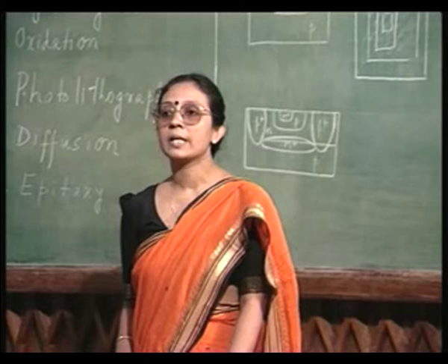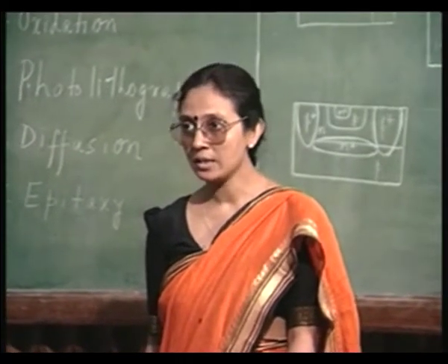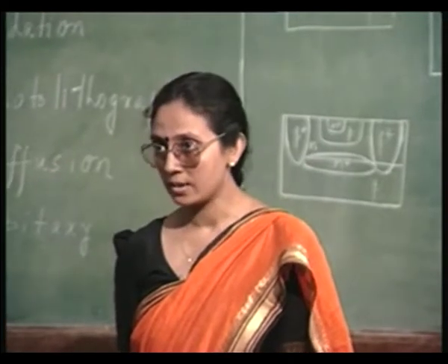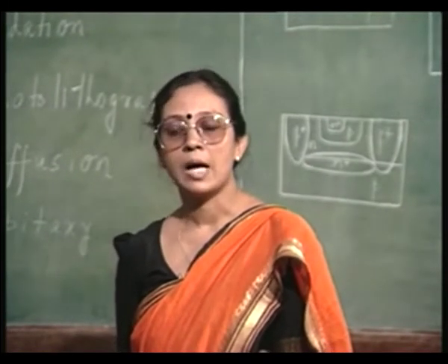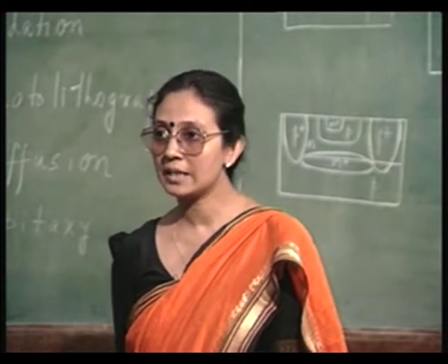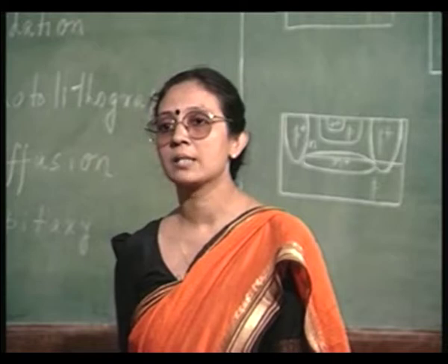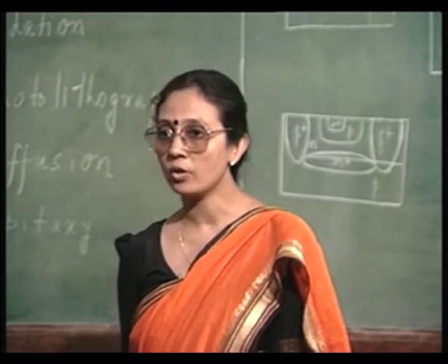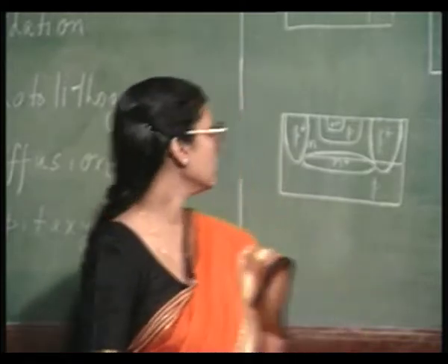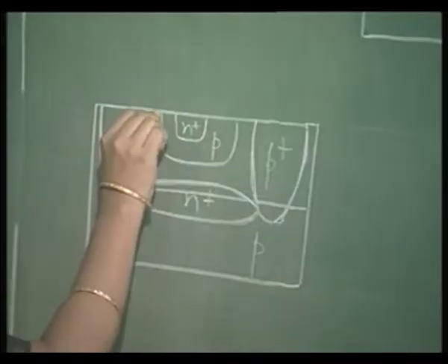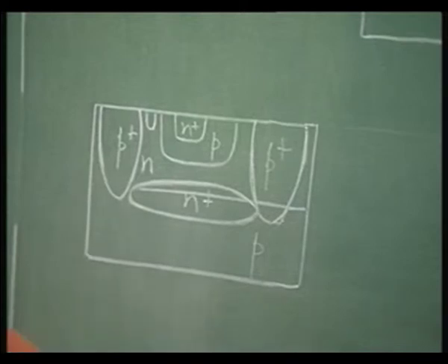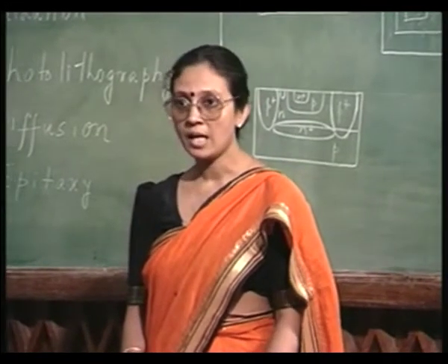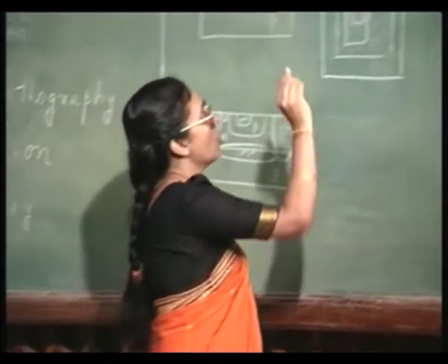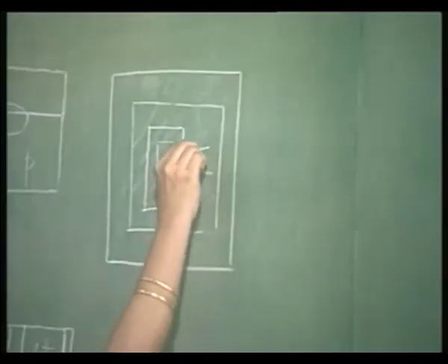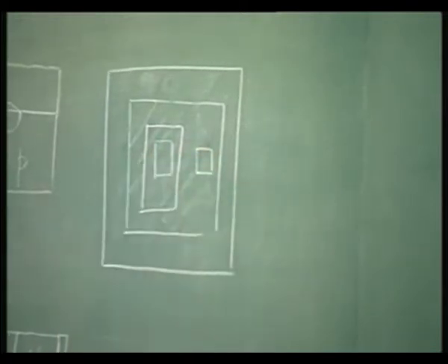So, in order to take contact from that lightly doped N region, you want to reduce the contact resistance. It is difficult to have a proper ohmic contact to a lightly doped N region. So, the usual practice is you have a small pocket of N plus diffusion for collector contact. You can have it here, a small pocket for collector contact. This needs no extra step. This can be done along with the emitter diffusion. Only thing is, for that you need to have a small opening inside the active region.